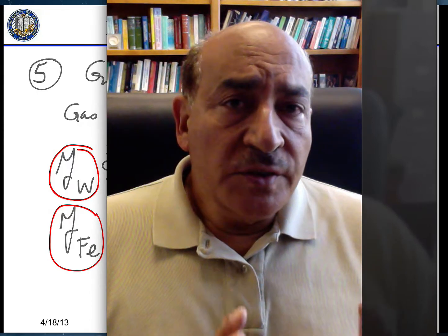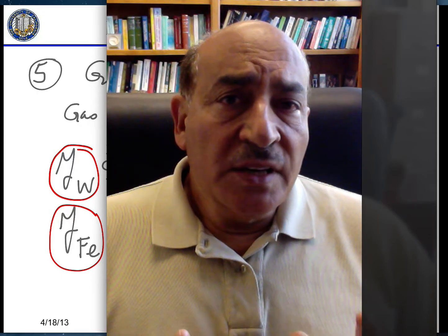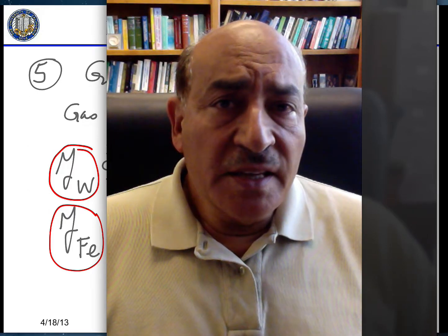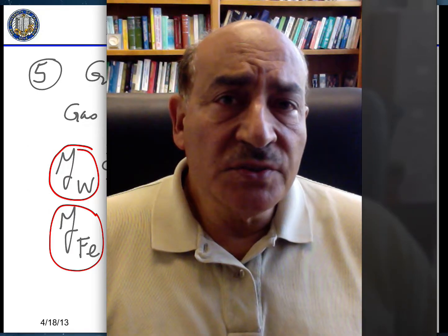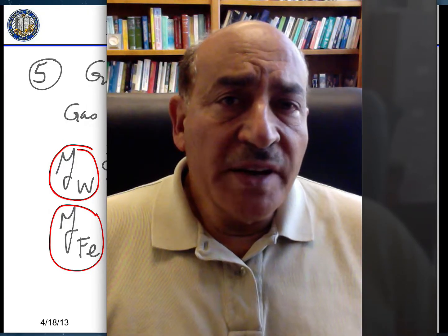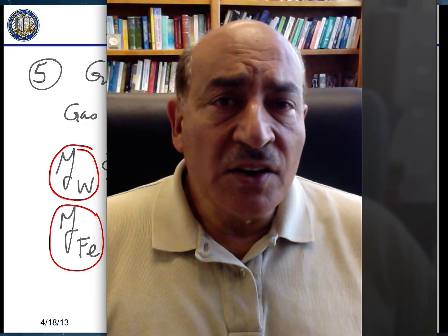And hence you're able to determine the equilibrium. Remember, the equilibrium is always the equality of the chemical potential. But when they are in solution, the chemical potential in solution is equivalent to the fugacity in solution, so you get the hat on top. And therefore, you have to have enough equations for each element to equate its fugacity in solution in phase alpha to phase beta, and you proceed with the solution as outlined here in this lecture.